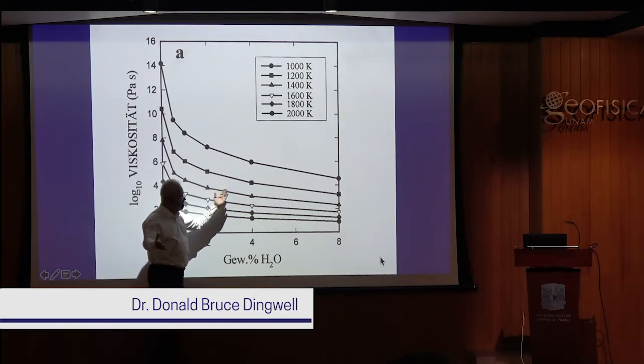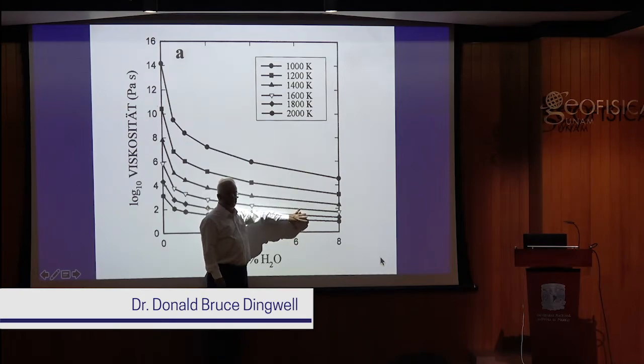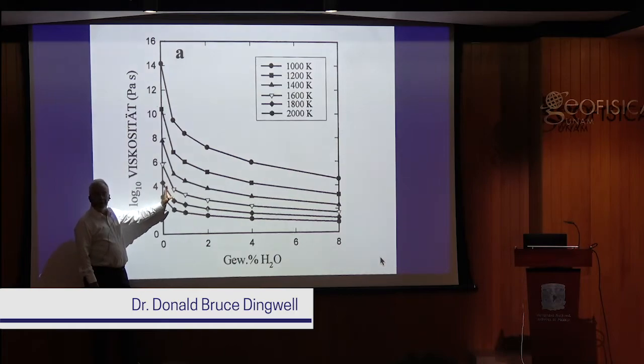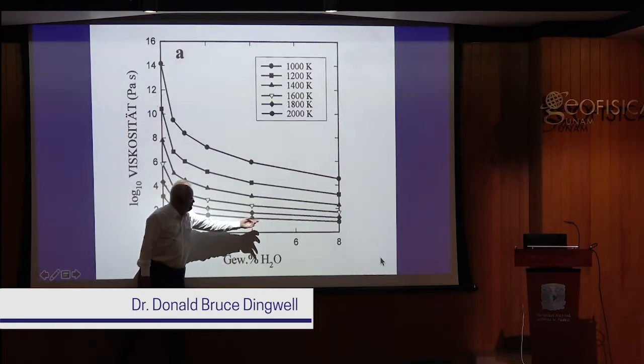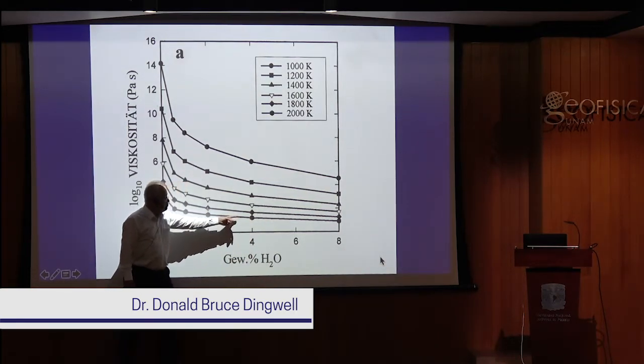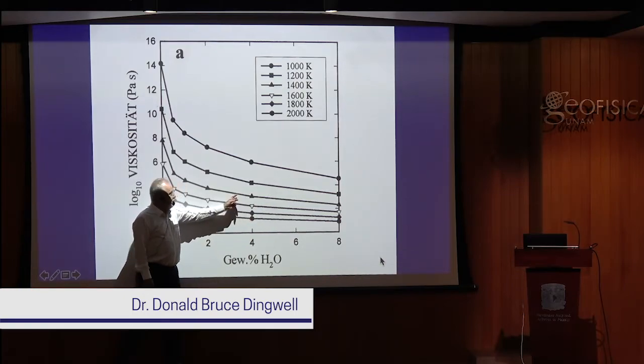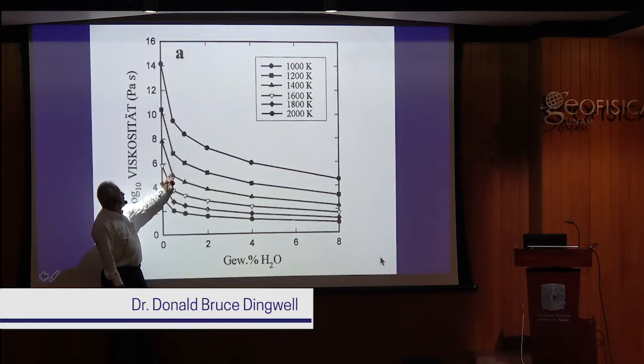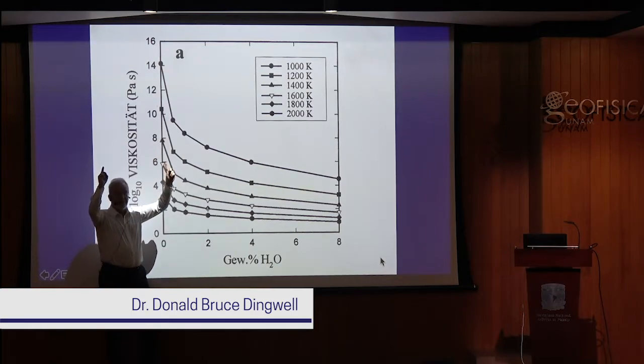So we know from melt inclusions that we can get large amounts of water before the eruption. We see them in the rocks, in the crystals, in the magma. But when we look at the matrix glass, we have water contents over here. So we've lost all this water, and as you see, losing a little bit of water is not a problem, but if I lose this water, then my viscosity rockets upwards.